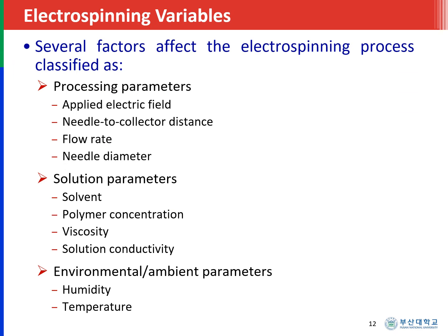To fabricate nanofibers from polymer solutions or melts using an electrospinning system, one needs to consider several electrospinning variables which affect the process. These factors are classified typically into three groups. One, processing parameters, which include applied electric field, needle to collector distance, flow rate, and needle diameter. Second, solution parameters, which include the type of solvent, polymer concentration, viscosity, and solution conductivity. And third, environmental or ambient parameters, which include humidity and temperature.